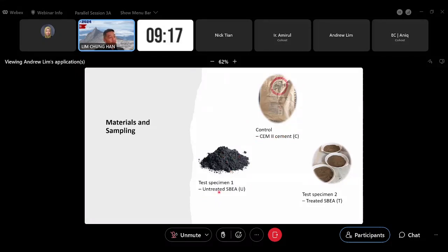Test specimen 1 would be SBA, the pozzolanic material itself. Test specimen 2 is SBA but treated. So the way I'm treating it is very similar to what Nick did, through calcination. We expose it to high heat for 4 hours, 700 degrees Celsius, if not mistaken. As you can see, from black color, it turned into reddish orange color after being exposed to high heat for 4 hours. Those are the 3 different samples that I'm going to use to test out the 3 methods.